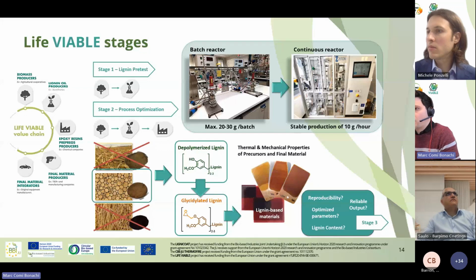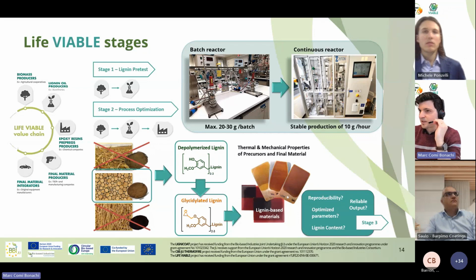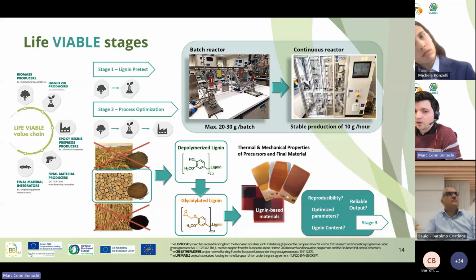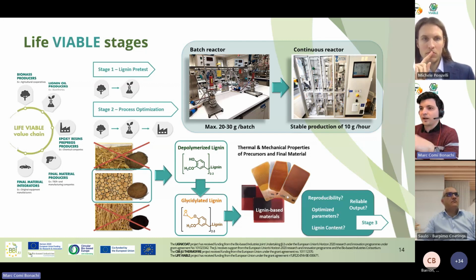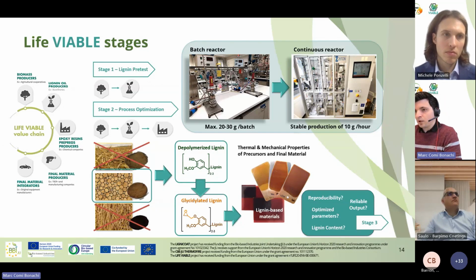In this case, we needed to pass to stage 3, the upscaling process, and we saw that corn stover, unfortunately, even if it is widely available in Europe, is very difficult to dry. Biorefineries are not ready to invest money in this kind of lignin obtention. On the other hand, we saw that wheat straw had a lot of solubility problems, which made the depolymerization and glycidylation processes very difficult. So we decided to discard these two botanical origins and move forward only with hardwood, which has well-established biorefineries in Europe.